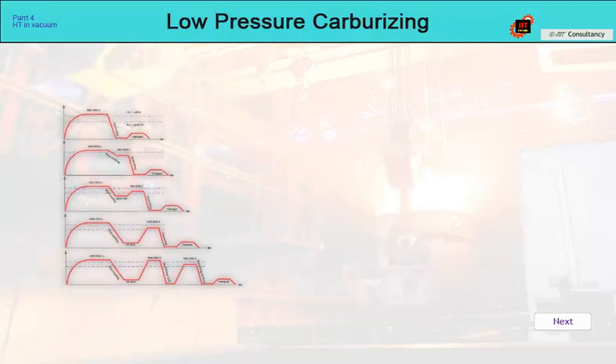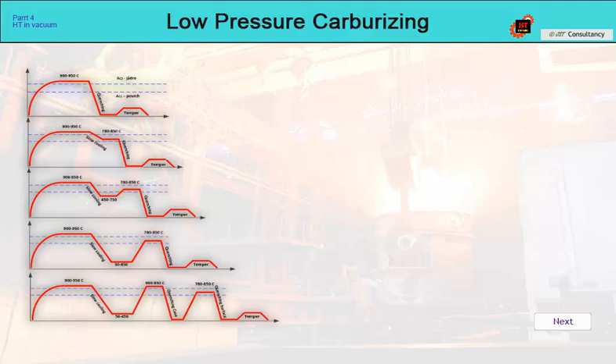Once we have carburized the parts, the next operation is quenching. This is fully up to the user. The quenching methods are described in detail in the course on classic carburizing. We will just review them. We can harden directly from the carburizing temperature, with pre-cooling to the optimum quenching temperature, with cooling below A1 temperature followed by reheating to the optimal quenching temperature, or with cooling below Martensite start and new reheating. Or we can even harden separately the layer and separately the core.